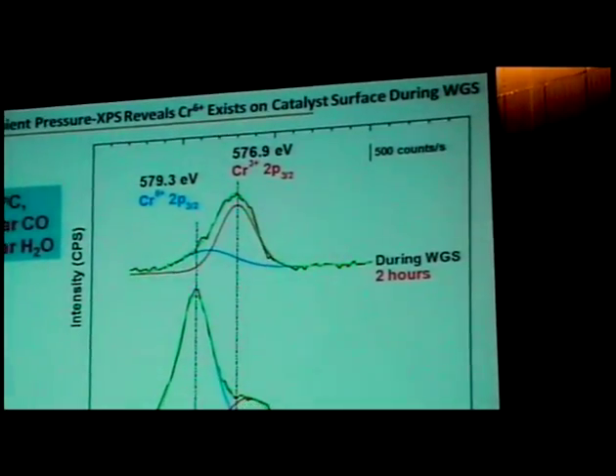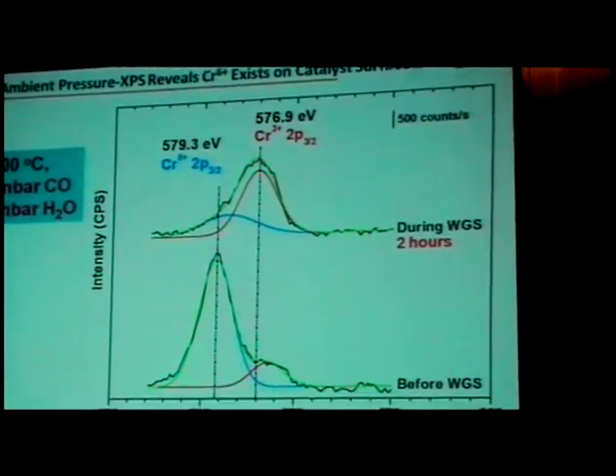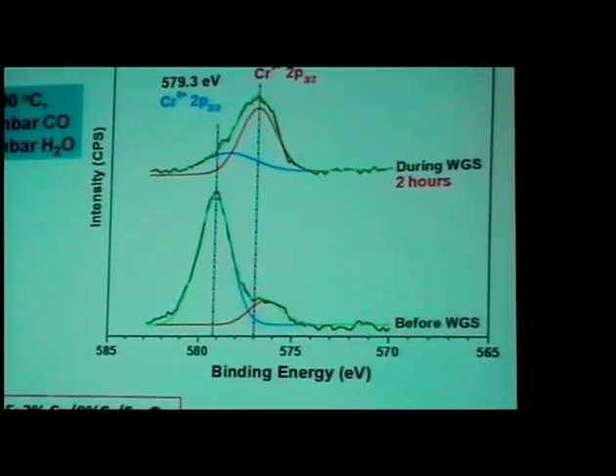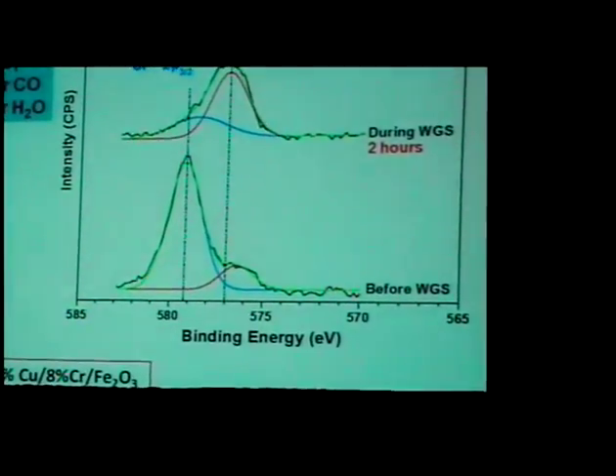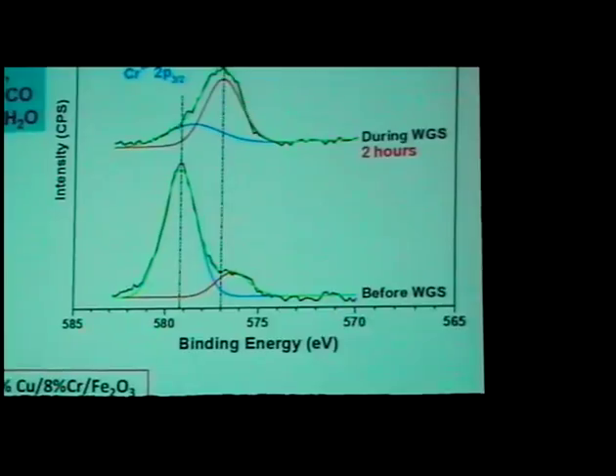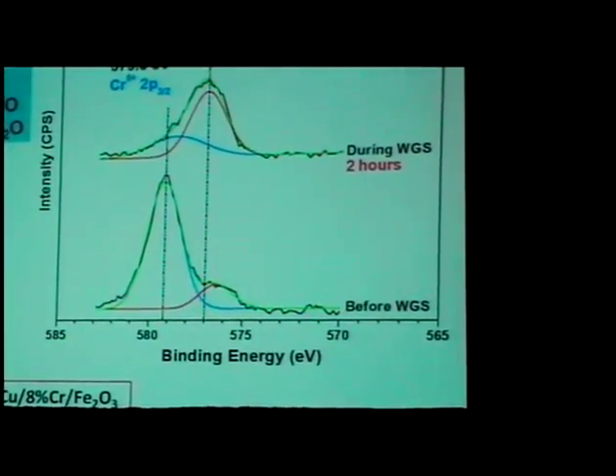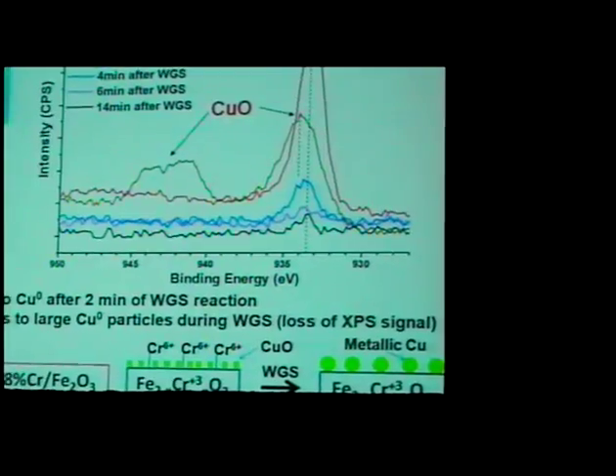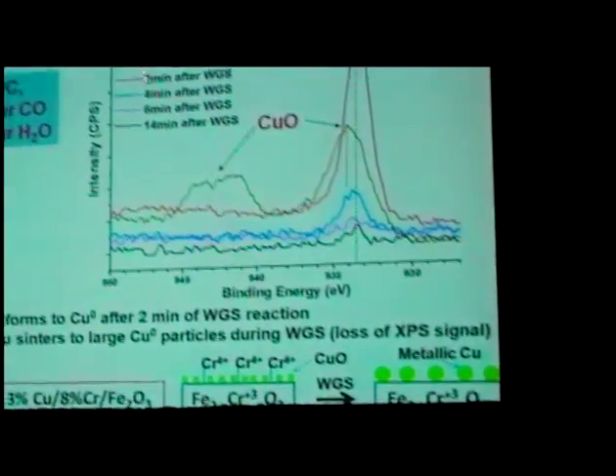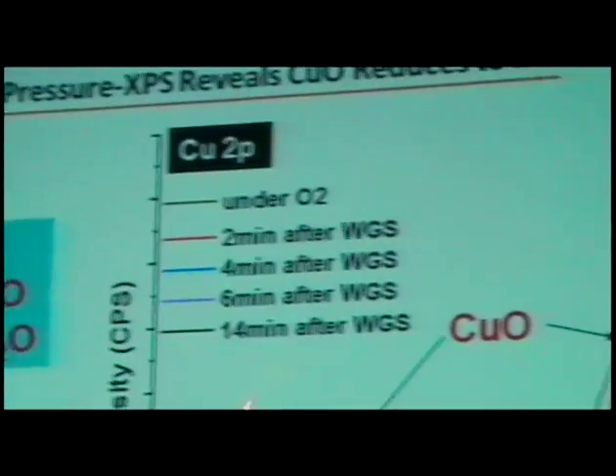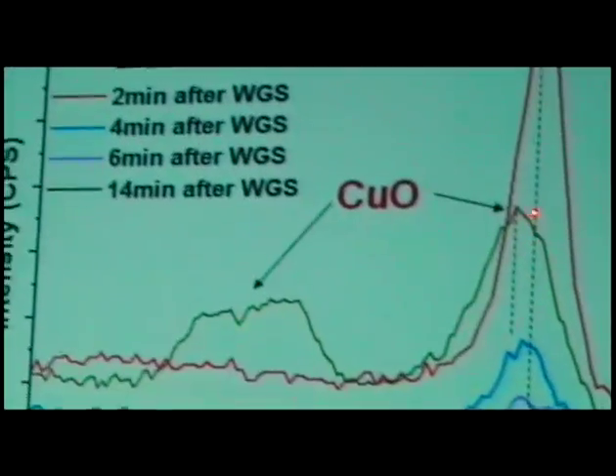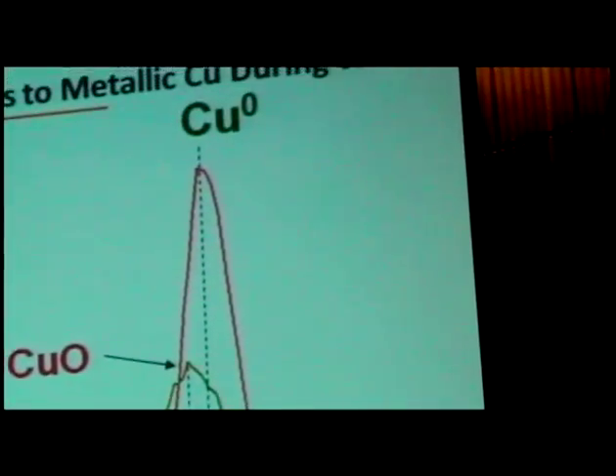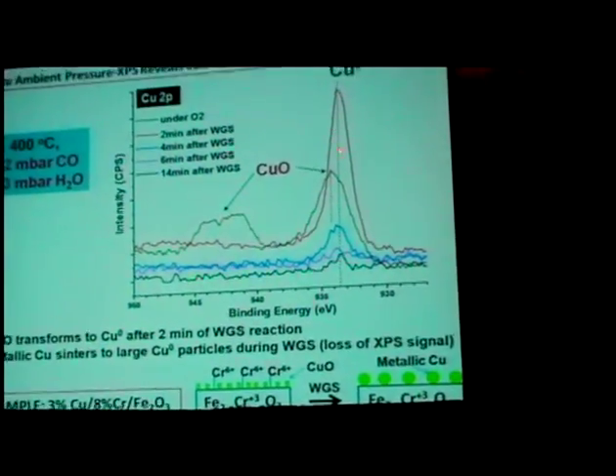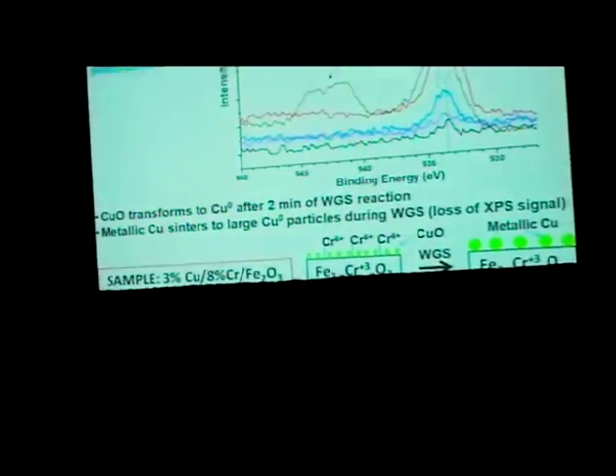chromium-3 present. So again, I forgot to mention that the chromium-6 being reduced to chromium-3 on the surface is responsible for the redox cycle in the chromium iron catalysts. This is the in situ XPS of copper, and initially it started out with the copper oxide being present, but very quickly we reduced it to copper metal.